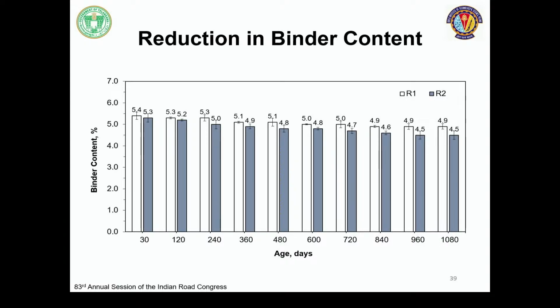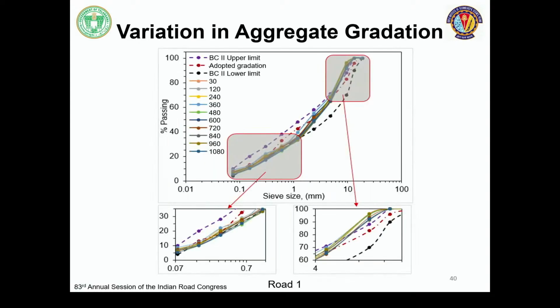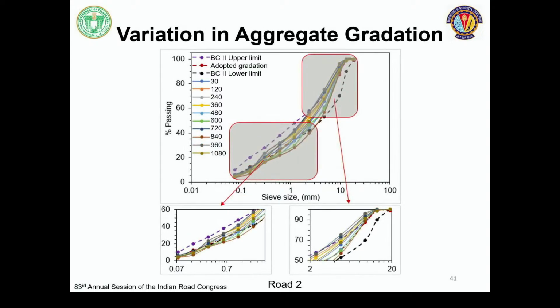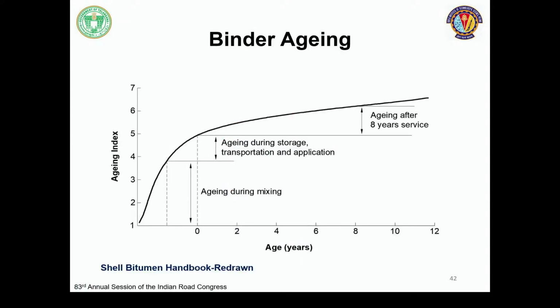Yes, 0.9% reduction. That was because of removal of the fine aggregate, and that fine aggregate was 150 micron. 150 micron, having more surface area, coats more bitumen, and when that is removed, there was literally a reduction in the binder content. So whether it was only on the top or the full layer, what we did was we sliced this into two parts and then tested it.